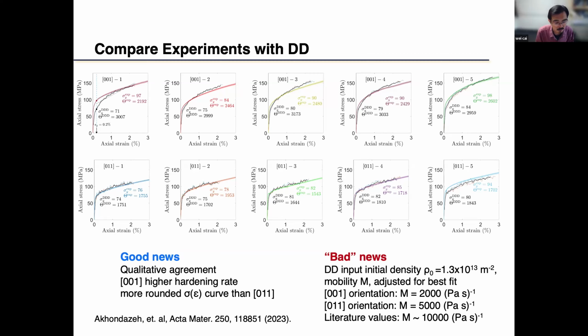Now, what are the inputs? Those inputs are not just fitting parameters; they are physical inputs, right? So one of them is the initial dislocation density. We don't know exactly what the initial dislocation density is, but the number we put in is quite reasonable. It's a little bit on the high side, but it's reasonable for undeformed copper. But the biggest problem is the mobility parameter, right? I mentioned that earlier. That's, given a certain stress, how fast the dislocation moves. And here we use a very simple linear mobility law. So we just say the velocity is m times the stress.